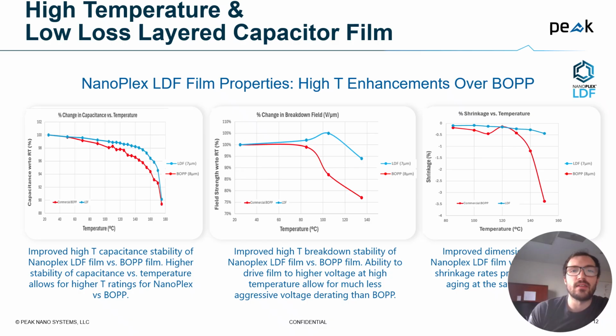And so again, this increased cutoff limit on the max operating temperature leads to a direct correlation in the net lifetime of the capacitor, where small hotspots in the device, in the case of LDF, don't lead to detrimental thermal runaway, just because the capacitor can be more tolerant to these conditions.